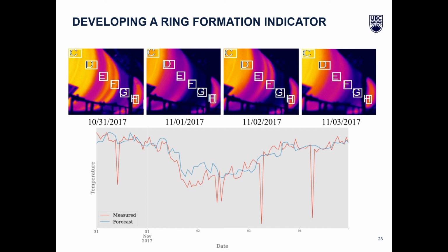Here we see the raw thermal camera images from 4 days in the top figure. Measurement area G is the 60-foot position which we are focusing on for this case study. October 31st is the image on the top left, which is used as a baseline to establish what the kiln shell temperature looked like before the ring growth event. The middle two images are the 2 days of suspected ring growth, and the image on the right corresponds to the day of ring decay. These raw thermal camera images help validate our indicator by confirming that a ring did grow after October 31st, and then it did decay a bit after November 2nd.